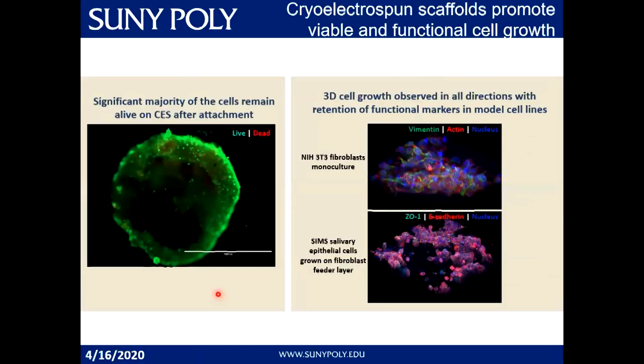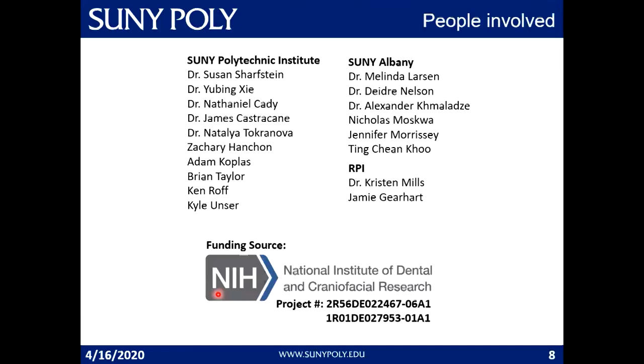We found that the cryogenic electrospun sponges had similar stiffness and relaxation time to the native extracellular matrix — a huge result for us. After characterizing our scaffolds, we grew cells in them to see if the cells attached and remained alive. Thankfully, the majority of them were alive on the scaffold with very few cells dying. When we tested for cell function using two different cell types, the cells were able to express the proteins needed to maintain their function and remained healthy. I'd like to thank all involved in this interdisciplinary project.